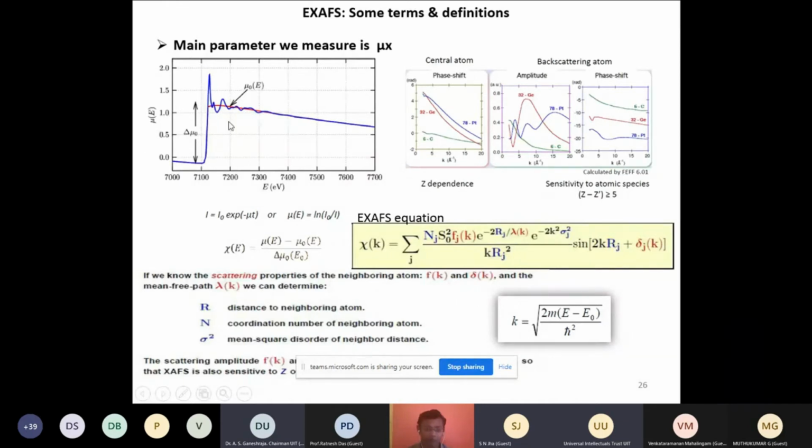It is an amalgamation of many sine waves of different frequencies and different amplitudes. So it is a convolution of various sine waves, produced due to different scatterers at different distances. We'll see more on how this is filtered for each frequency.